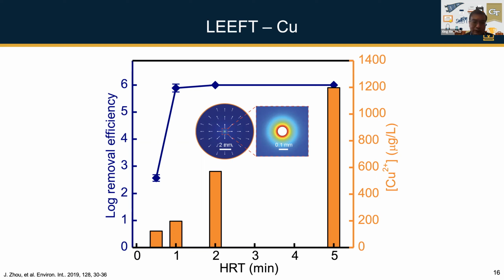We came up with this idea from our previous work. When we did the water disinfection with LEEFT itself, because the electrode we developed, as you can see, is based on copper, right? So we have the copper film, we have a copper ring electrode, we also have a center electrode which is based on copper. We do notice some copper concentration, we have copper release in the system.